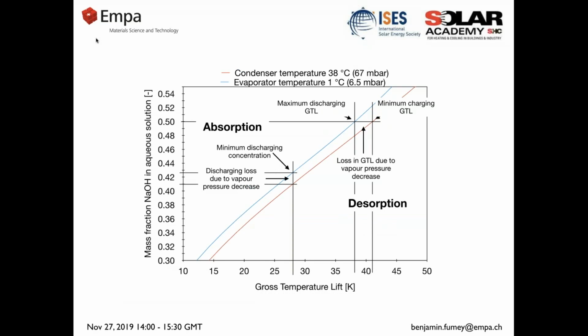When we look at the vapor pressure equilibrium lines as stated based on the temperatures that we define, we see here that because in the charging we have a higher condensation temperature than in the discharging, the evaporator temperature, we of course have gross temperature lift just due to the specific application. And also, more importantly, what we see here is that in the discharging, because of the low vapor pressure, we cannot discharge to the same final mass fraction as would be possible with a higher evaporating temperature. So just pointing to the fact that it's very important to have a common basis on the temperatures that we work with.